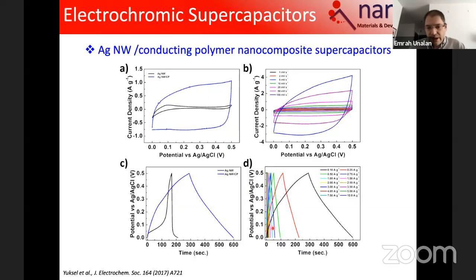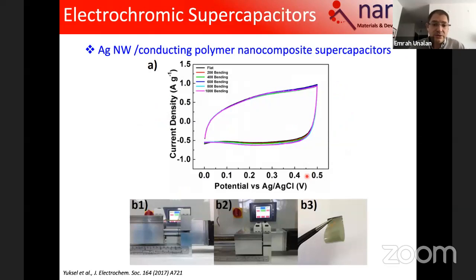And on the bottom, you have these charge-discharge curves. And the more triangular this thing is, the more it means that you can charge and discharge in a symmetric fashion. That means that your device is reproducible. And with our polymer, we don't really have so much deviation from the triangle behavior. So that was quite a promising fact.